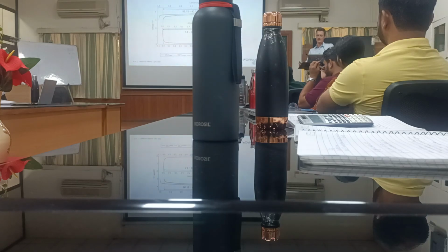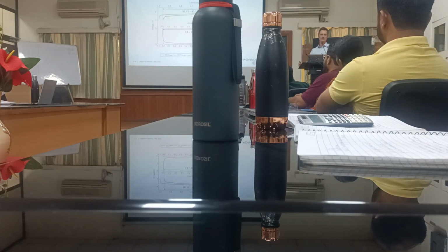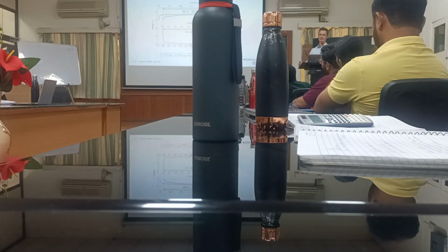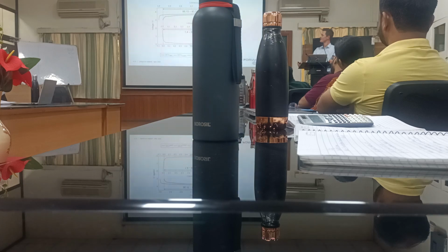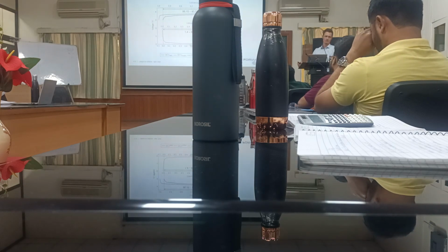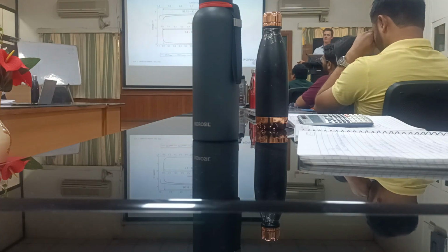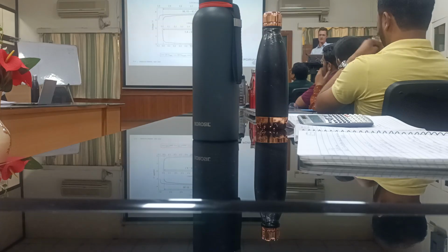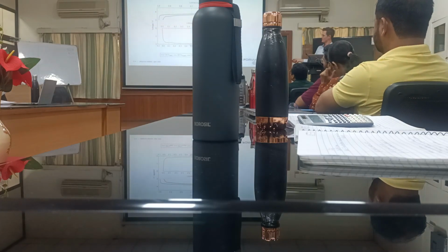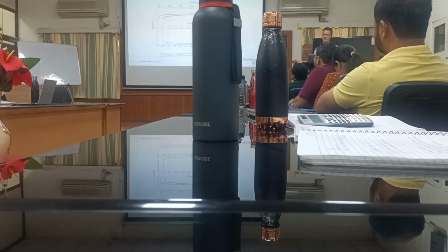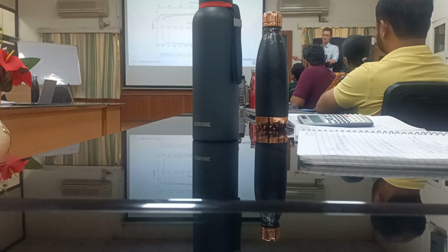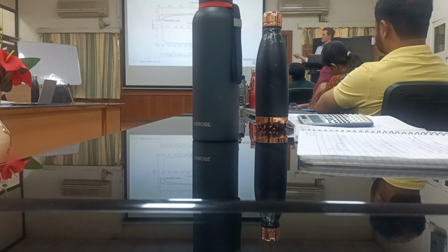And this have to be designed, it actually means that the size of the electrodes and the thickness of the layer of the electrode is different for both sides. I mean, it makes sense, anode and cathode, they have a different thickness and they have a different weight. So that means that you have a different amount of active material. But this is the reason that you need to balance the lithium storing capability. So, yeah, just to be clear, this is over-dimensioning of the anode. That is, of course, not good for efficiency, but you must do it for this system. In the beginning, usually you also lose a little bit due to formation.